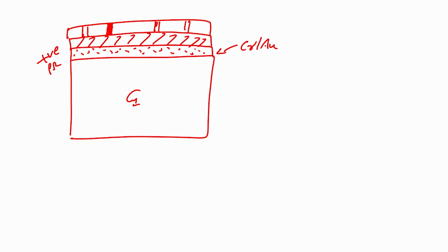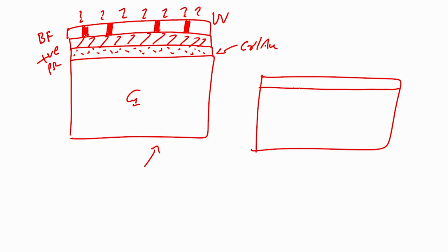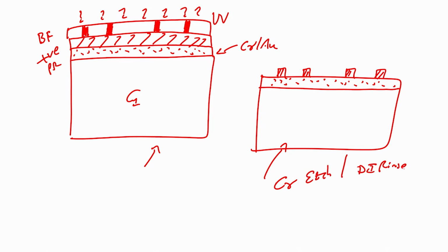something like, I am just showing representative diagrams, right, bright field mask, then you expose the wafer with UV light. After exposing the wafer, you develop this glass wafer. When you develop the glass wafer, what will you have? You will have your chrome gold and your photoresist protected in the area which was not exposed, since it is a positive photoresist, right. Then you dip this wafer in chrome etchant followed by DI rinse, then gold etchant followed by DI rinse, right. When you do that, what will happen?